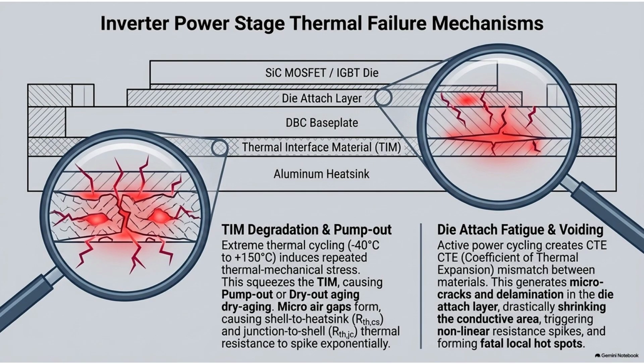And to make matters worse, extreme sustained heat can cause the silicone oils inside the TIM to simply evaporate or dry out over time. Leaving what? Just dust. Basically, yeah. It leaves behind a brittle powder that eventually just crumbles away. And when that paste is gone, whether it pumped out or dried out, those microscopic valleys come back. The air gets back in. And the return of those air gaps is catastrophic.